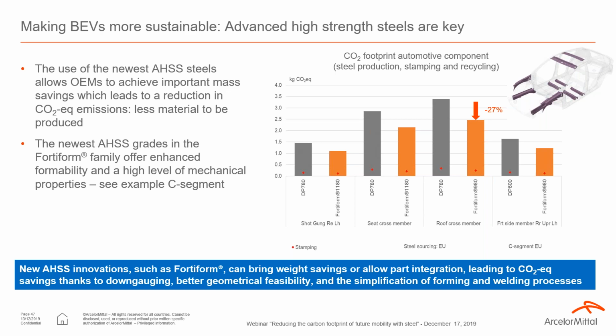So here I would like to highlight the added value of our new Fortiform steel grades, which is a new family of advanced high strength steels. These grades, with mechanical properties up to 1200 megapascals, bring an enhanced formability, which is best in class for cold stamping, and in fact it allows quite directly to switch from conventional DP 800 to these Fortiform solutions. Depending on different applications, we saw that we could achieve very interesting mass savings, which would also bring a very good reduction in CO2 equivalent emissions.